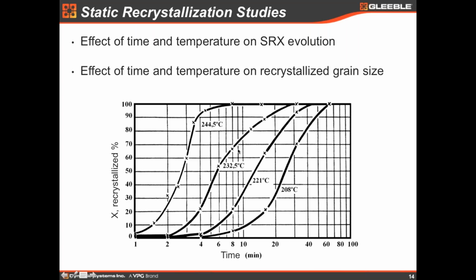So the same thing can be done. No, this is time consuming, of course, but at least you can generate these microstructures at the Gleeble. And not only the recrystallized fraction to check the kinetics, but you can also measure the grain size. So you know the grain size and the static recrystallization evolution.